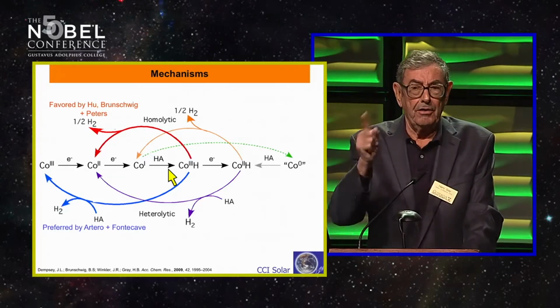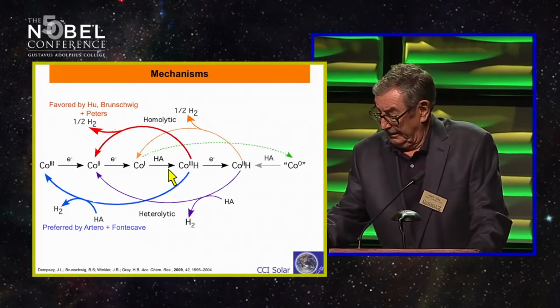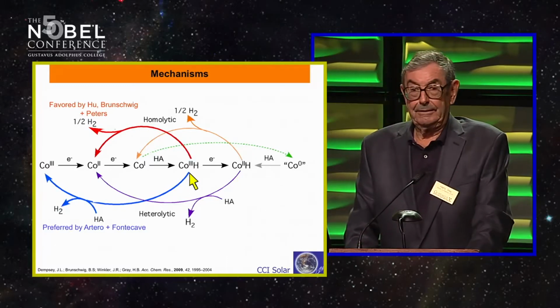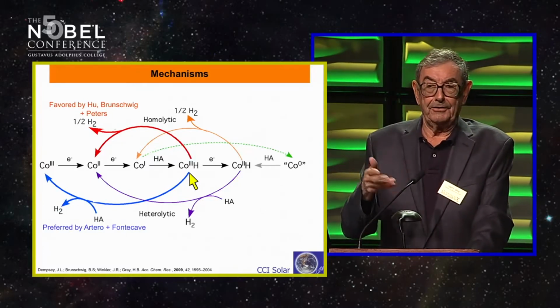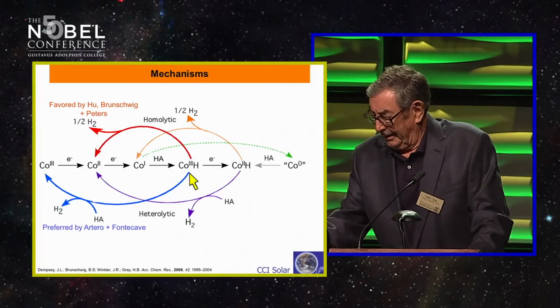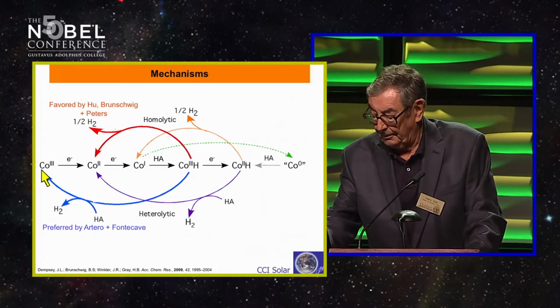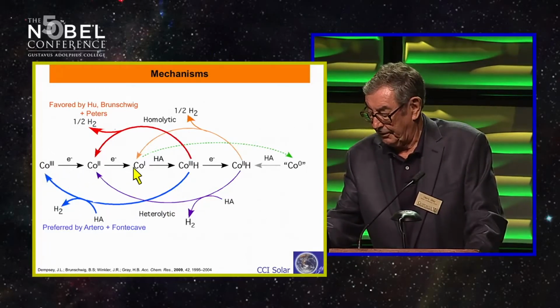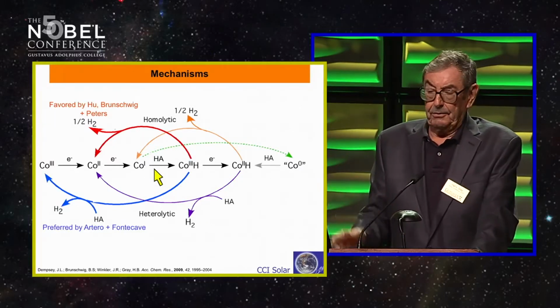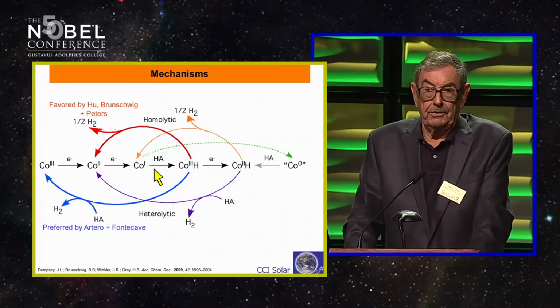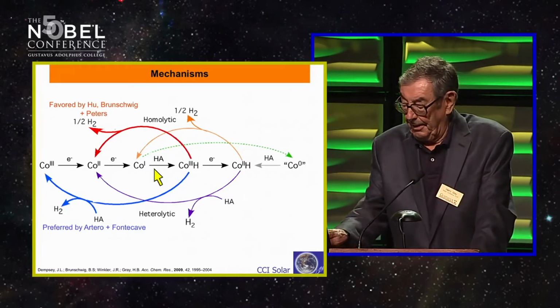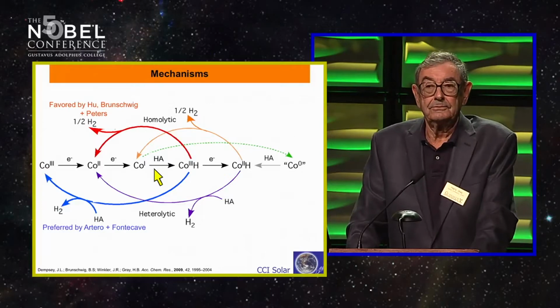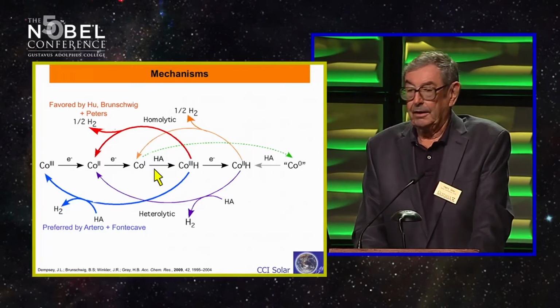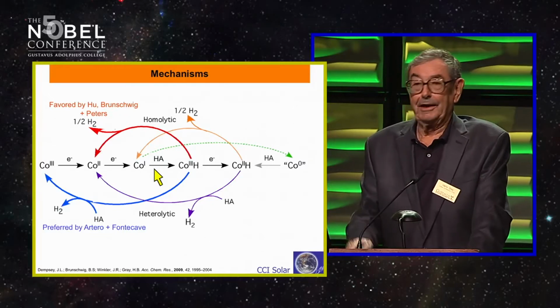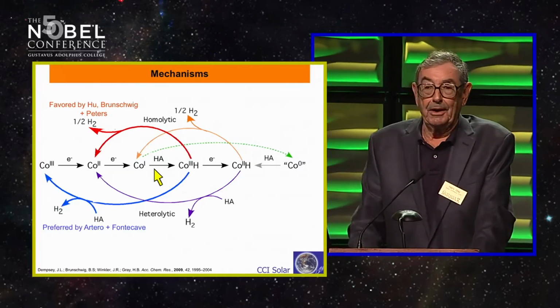The French said, no, no, no, no, you Americans never get it right. They weren't from Minnesota, they're non-Minnesota Americans. They said, you can take this cobalt-3 hydride and just protonate it off directly to make hydrogen and end up with cobalt-3, which you can then come back in by electrons into the cycle. Well, then there was some American work that showed that cobalt-3 was not produced at all in this cycle, thereby showing the French were probably wrong. There were brief parties in the US celebrating this, figuring this mechanism, the American mechanism, had to be right.